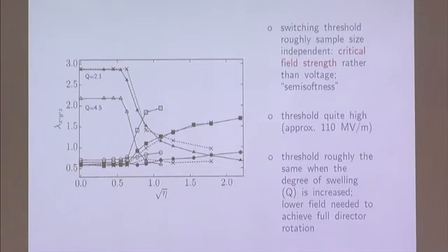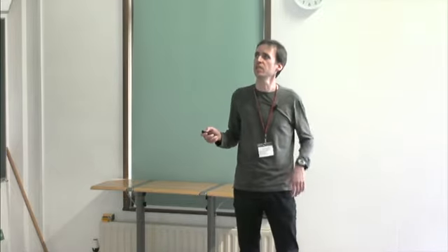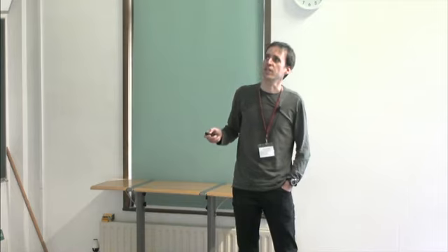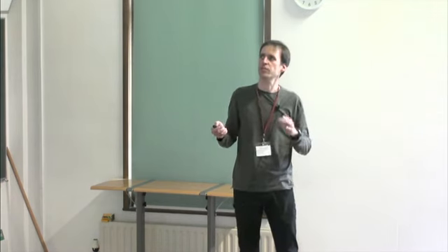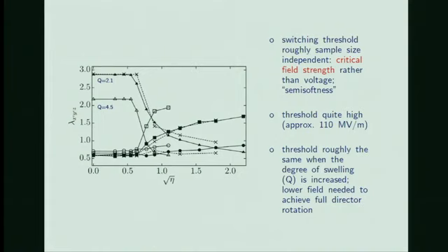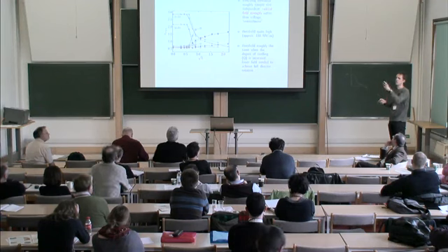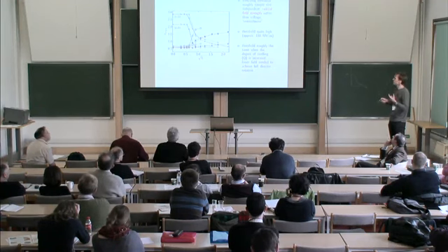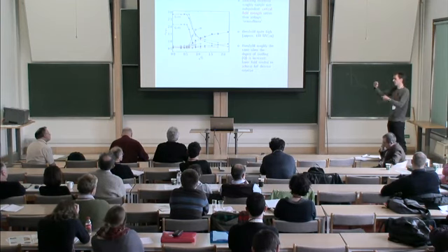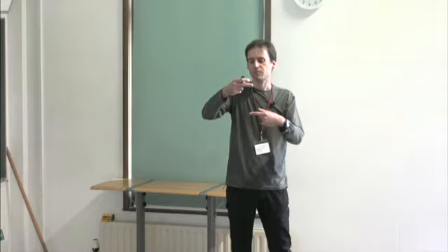But okay, when talking of semi-softness, it's maybe better to be a bit more careful here, because in addition to seeing a threshold, it would be necessary maybe also to look at what happens to the polymer strand end-to-end distribution upon this rotation. It turns out that our systems are rather small, so it's not really easy to get good statistics to have reliable data on this issue. And probably this distribution is not really conserved because our domain size, let's say the distance between the domains, is quite comparable to the actual crosslink to crosslink distance.